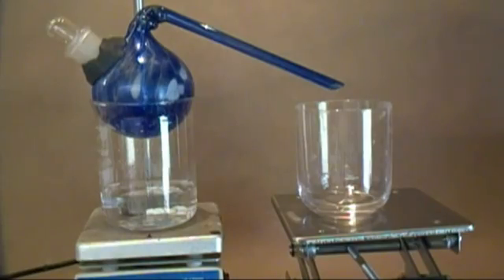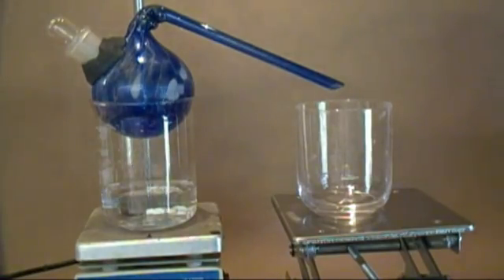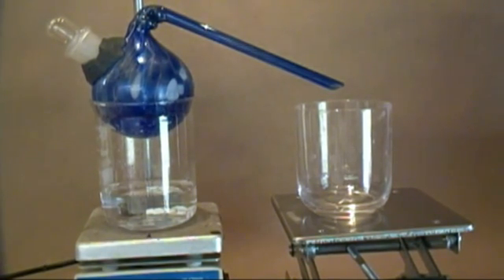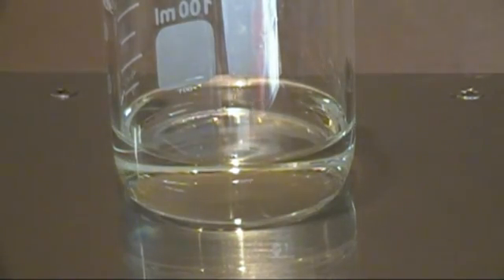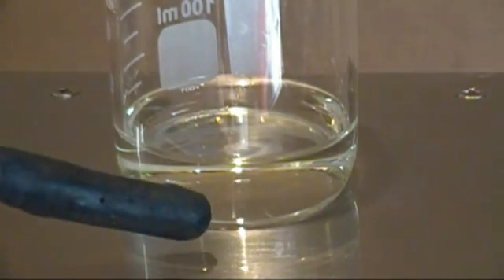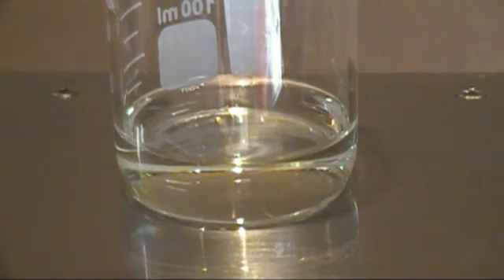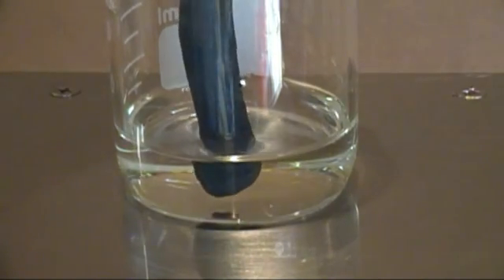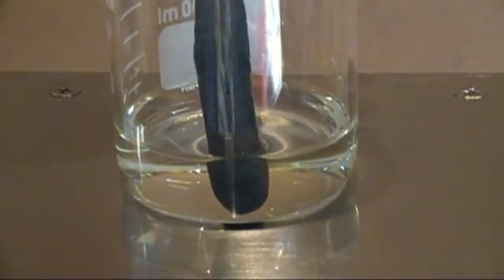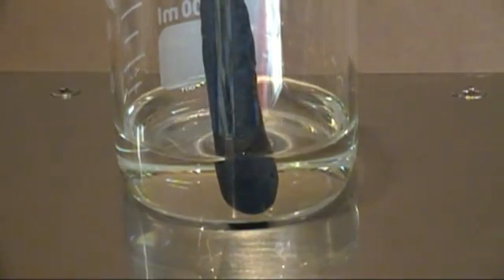After a couple hours, I set mine up for steam distillation. I chose steam because I did not want to shatter it with direct heat. While we wait for the water to boil, let's look into the epoxy. This epoxy is pretty amazing stuff. Here's a beaker with 31% HCl in it. Let's drop in some of the epoxy and see what happens. Nothing. It's non-reactive with HCl. Or at least it's non-reactive at room temperature.